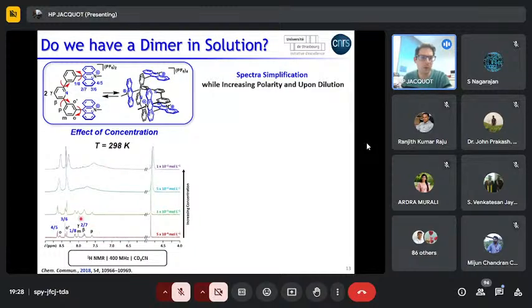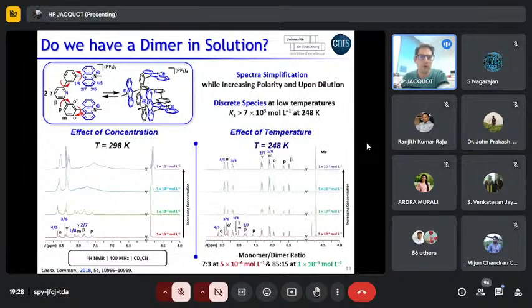And upon dilution, we have a simplification of the NMR, meaning that we dissociate the assembly and then we form a monomer. Then when we took these 4 solutions at low temperature, what we saw is that we have a new chemical species for the most concentrated solution, which is actually the dimer. And when we dilute at low temperature, this time we see that there is the presence of the dimer and also the presence of the monomer at the same time.